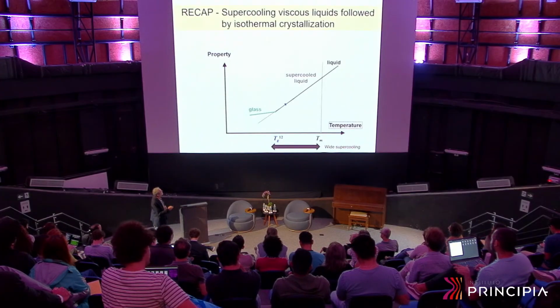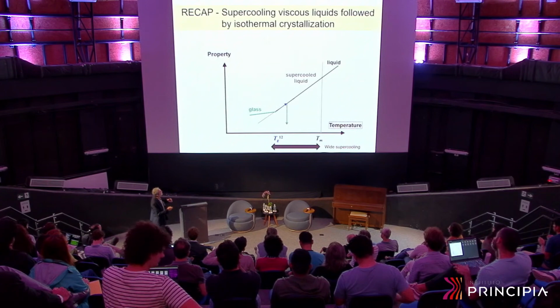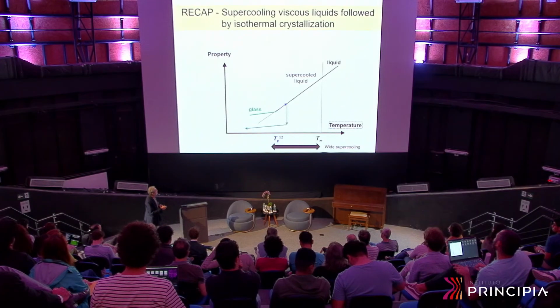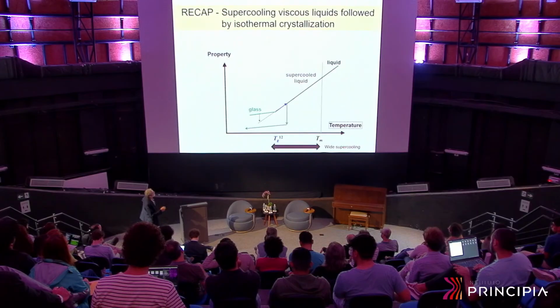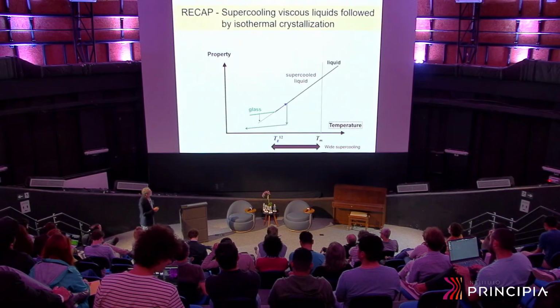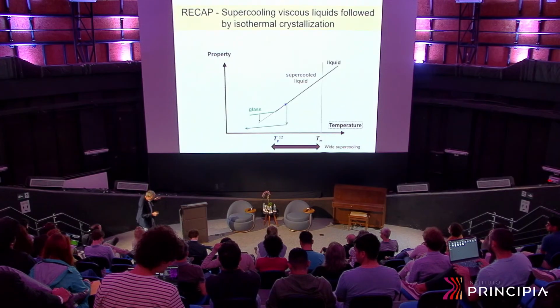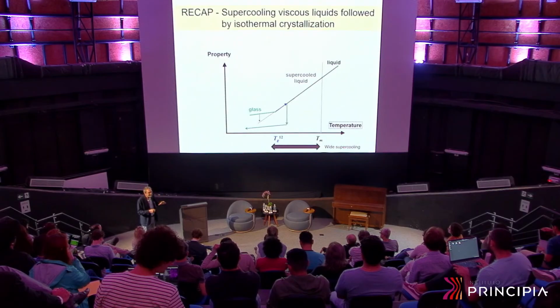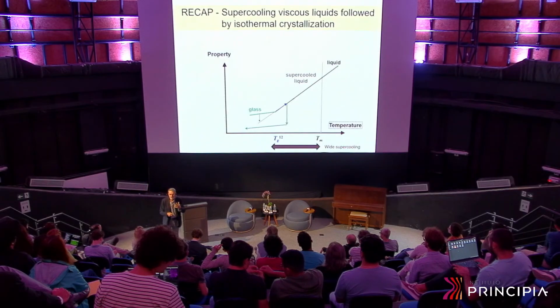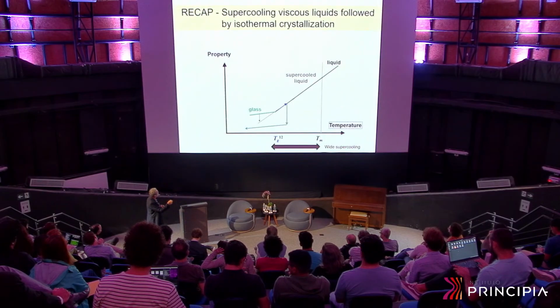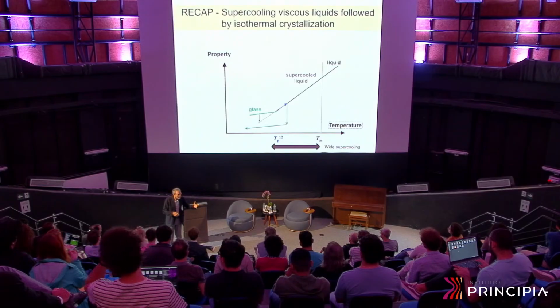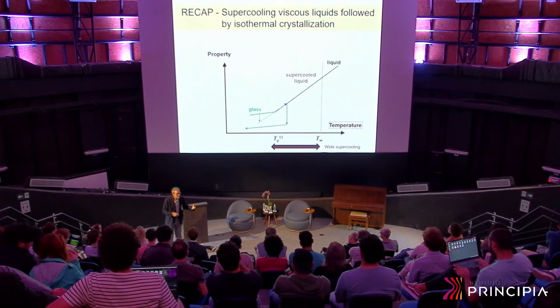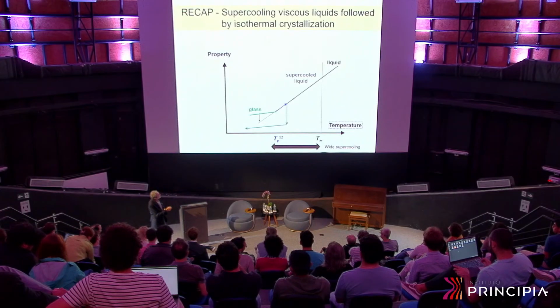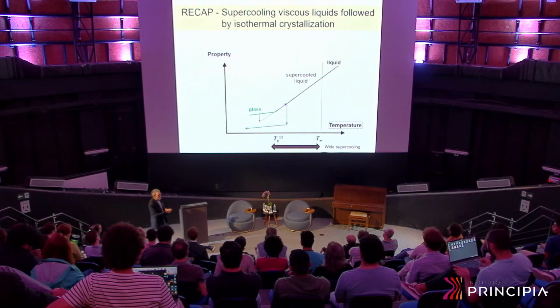Because if you wait, well, just before I tell that, if you heat them up a little bit, they will easily crystallize. Now, if you come back at a temperature, say, a few degrees below the glass transition, glasses will relax, or their structure will accommodate. All glasses are relaxing. These glasses here are relaxing. Of course, if you are well below the glass transition temperature, at room temperature, it will take a very long time. They will relax, but it will take a very long time. You cannot wait for this. So normally, you heat up a little bit just below the glass transition to follow the relaxation process by measuring any property.